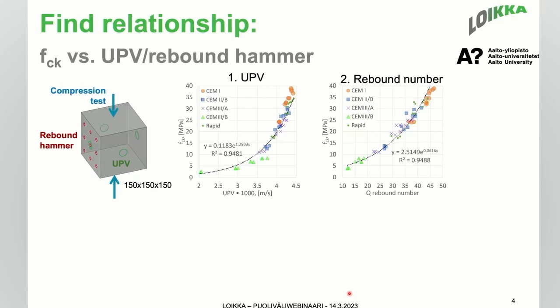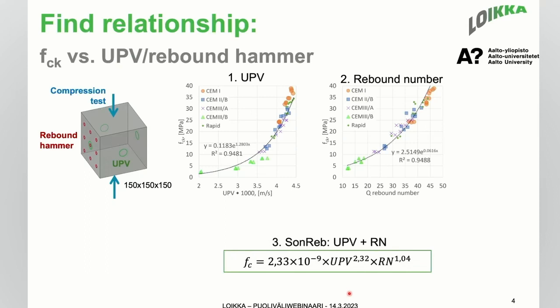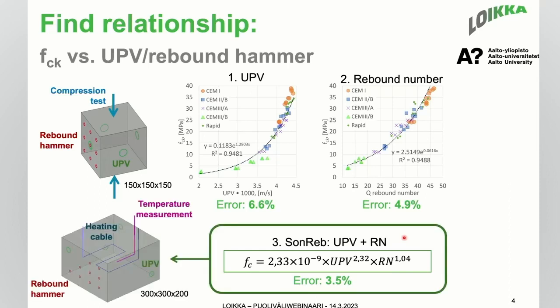That is why we combined and estimated early strength development with SonReb method, which takes into account UPV and rebound number. And it shows us the less error. That is why this method was used for further testing, and we estimated early strength development for big cubes with SonReb method.